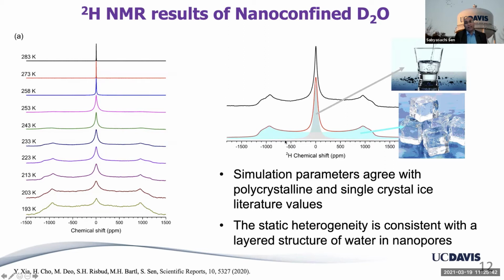That's not to say that this is coming from crystalline ice. This could be amorphous ice. We don't know. And this could be a mixture of amorphous or crystalline ice. We don't know about those things. But all we know is that there is a solid-like component and a liquid-like component.